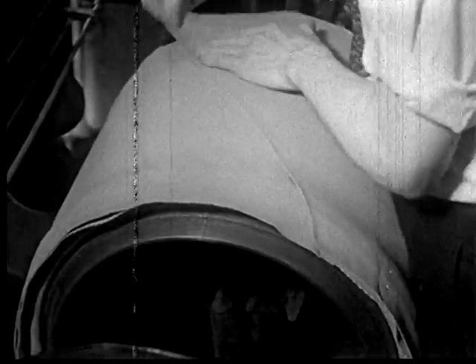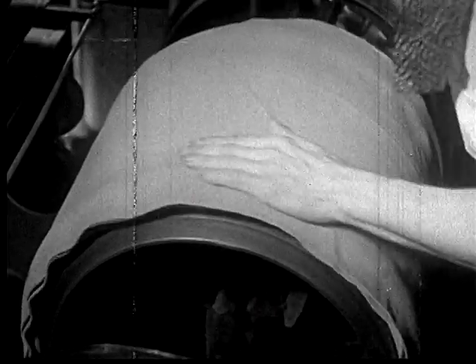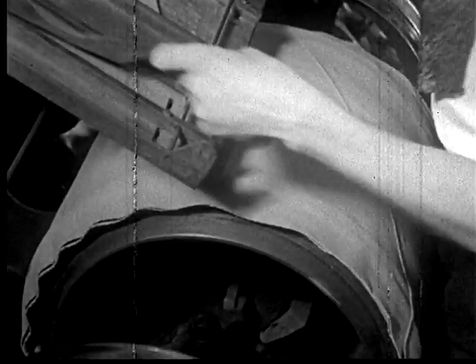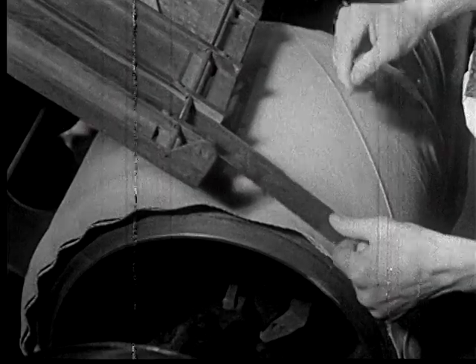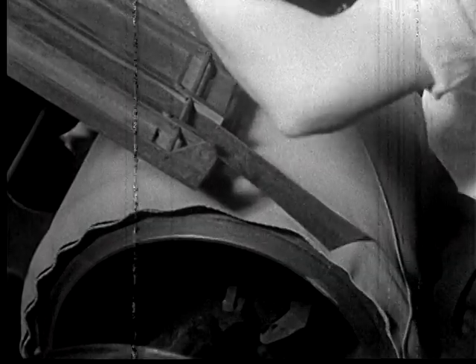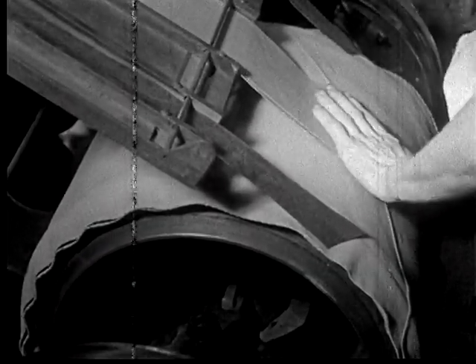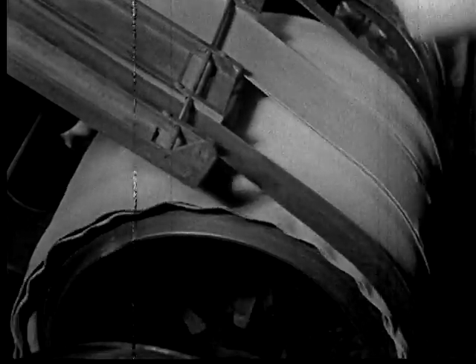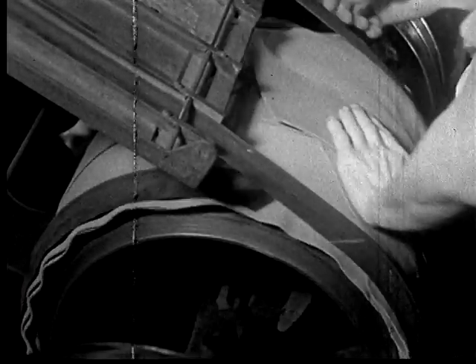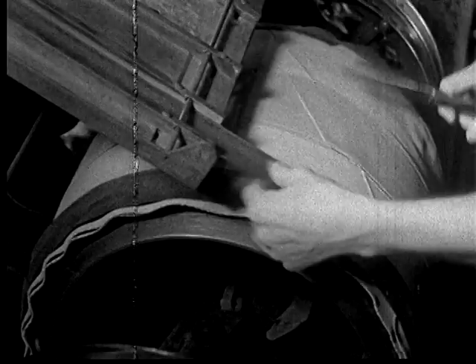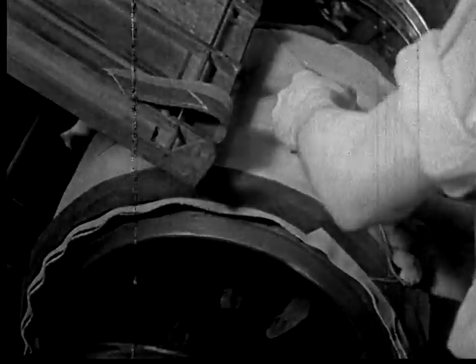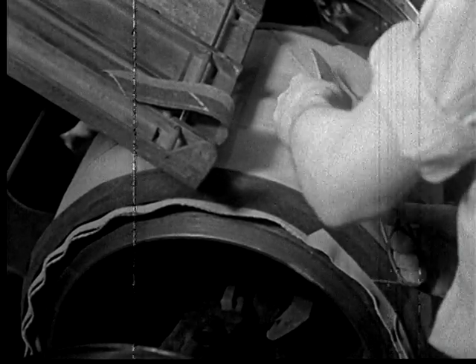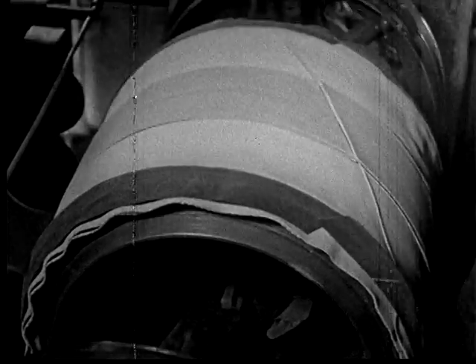One of the most common causes of premature tire failures and blowouts is the separation of the carcass and the tread. In order to eliminate this hazard, Brunswick has developed the double shock absorber unit. That's the center unit being applied. It consists of 2 extra layers of cord material treated and coated with a special cushion compound, which not only ensures positive adhesion of carcass and tread, but also protects the body of the tire from high-speed road shocks by absorbing and distributing them over a wide area of carcass.